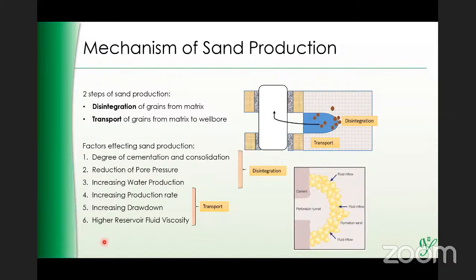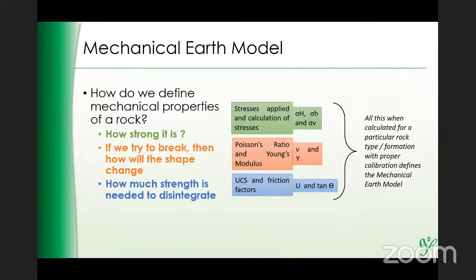And finally, the reservoir fluid viscosity. Because of the viscosity, the drag forces are very high on the sand particles. So with the drawdown, the drag forces, the sand gets disintegrated from the matrix, comes into the wellbore. And if your velocities are high enough to overcome the transport velocity of the sand particles, it will come to the surface. That way you get the production of sand onto the surface.